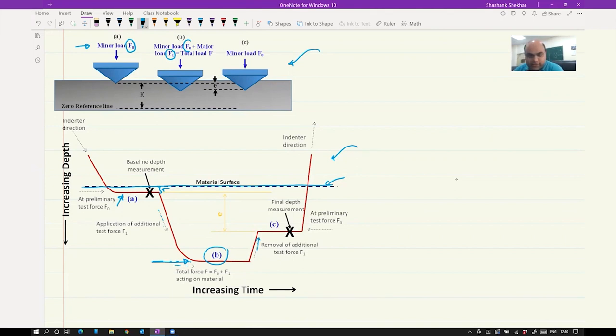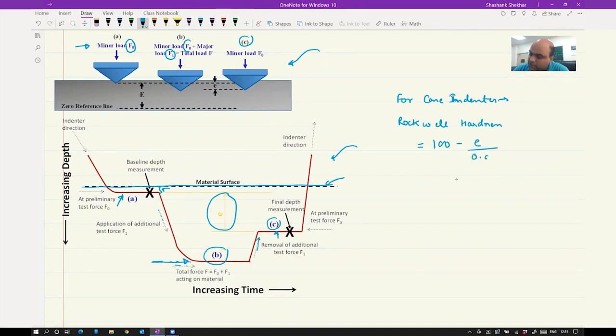After you remove the additional test force F1, your depth position is going to be this one, C. Here you have C, and here also you have C. Now you have only the minor load F0 applied on your sample. You measure this distance E, and you use this to measure the hardness of your material on the Rockwell scale. If we use a cone indenter, the Rockwell hardness will be given as 100 minus E divided by 0.002.